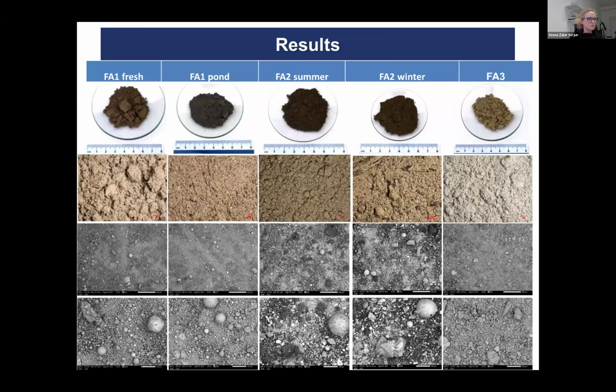So 5 different ashes were used, 4 of them from Slovenia and 1 from a neighboring country. FA1 was collected fresh, directly from the production. FA1 pond was collected from the landfill. FA2 was collected from the summer regime, FA2 winter from the winter regime, and FA3 was collected from the neighboring country. Although they are all specified as fly ashes, FA2 samples are basically co-combustion samples because during the incineration they use some wood chips, and the quantity of wood chips used is larger in the winter because they are increasing the calorific values.